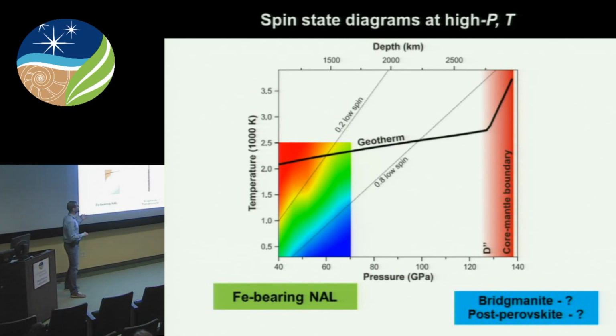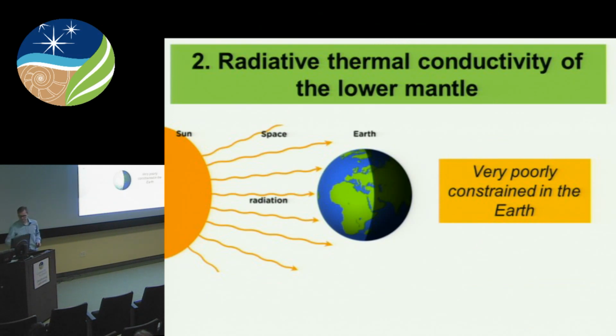We can now extrapolate this onto the whole lower mantle PT scale, and we will see that if the lower mantle was made of NAL, which it is not, we would have known its spin state by now, and only near the core mantle boundary would we get a pure low spin state. What I want to point out is that because of crystal chemical similarities of NAL with bridgmanite and post-perovskite, it is possible that these two lower mantle minerals have similar spin state diagrams.